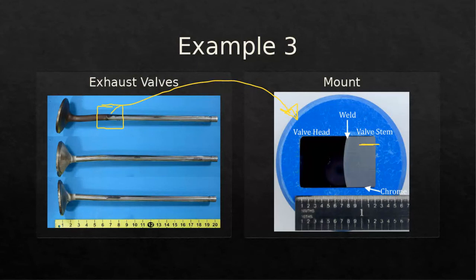So for me to get that particular sample, I had to make two circumferential cuts, one in the valve head, one in the valve stem. Then I followed through with an axial cut through the middle. Now, you can see that I have a dark line here. That is a chrome layer. So that means this entire piece of this valve stem is chrome plated. The chrome plating ends right at that weld interface.